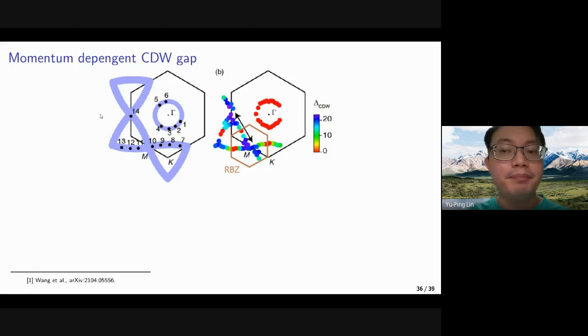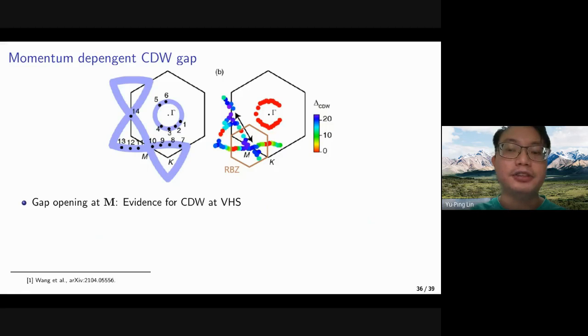It has also recently been observed that the CDW gaps are indeed momentum dependent. And we can look at the gap structure in the reduced Brillouin zone here, centered at the M points. So near the gamma point in the original Brillouin zone, it seems the charge density wave seems to be gapless, and because the Fermi surface around here occur from the other larger lattices than the vanadium kagome lattice, it may also just mean that the charge density wave only develop on the vanadium kagome lattice. And from the gap opening at the M points, we find the evidence of the charge density wave at the Van Hove singularity.